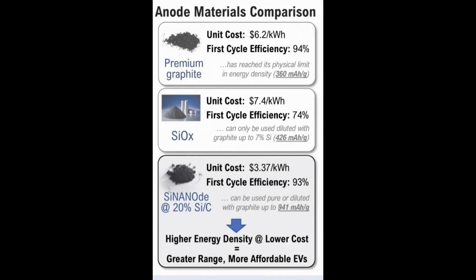When we do the composite, we start with a graphite that maybe has 94% ICE, initial coulombic efficiency, and we add 20% silicon or whatever, we then blend that and make an anode. The cycle loss is the same as with graphite. So that's the answer. Now, how do we get there? I can explain to you in a minute.